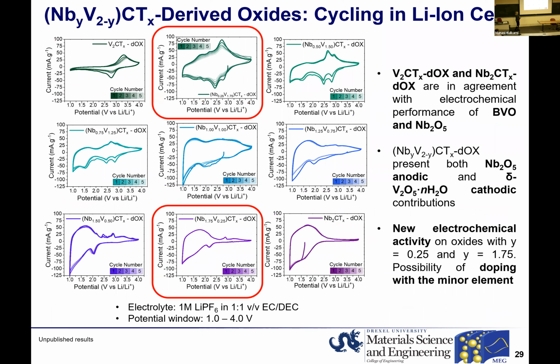However, through electrochemical cycling, we noticed that the shape of the CV curve that corresponds to the low concentration of niobium and high concentration of vanadium looks very different from the bilayered vanadium oxide, while the XRD pattern shows almost only bilayered vanadium oxide in this case, which implies that we were able to achieve some doping of niobium into vanadium sites. This is the direction that we want to explore further, because niobium-doped bilayered vanadium oxide has never been synthesized before. We are hoping that with these solid solution MXene precursors, we can achieve that and modify the electrochemistry of the final product in a way no one was able to show before.